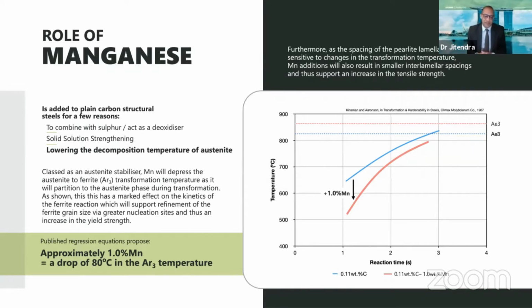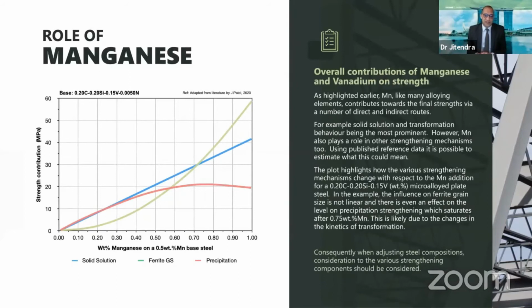And this graph just shows that. But again, it's an expensive way to trigger this mechanism to develop a finer grain structure. So these are the two things which I'd like us to bear in mind of what manganese does: it helps with solid solution strengthening, but also, as I said, it depresses the Ar3.